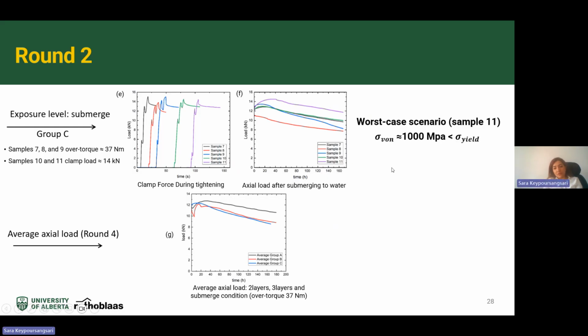So we measured the von Mises stress by considering this fact that for sample 11, which is the worst case scenario, the moisture only affects the axial stress, and the shear stress is only due to the installation. And also based on the previous round, we found that there is a relaxation. So we measured the von Mises stress, and we found that in the worst case, which is sample 11, the von Mises stress is below 1000 megapascal. It should be mentioned that we opened all the samples, and we couldn't find any failures in self-tapping screws, even under the severe moisture content change.